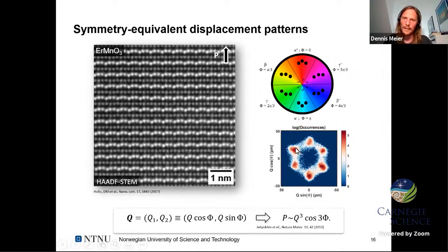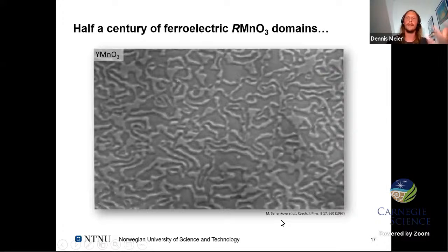When you look at order parameter space, we see these red dots here, which illustrate the 6 ferroelectric, structural domain states. And then, as I said, only as a secondary effect, due to the coupling, the polarization comes in because of these structural changes, and we also get a ferroelectric polarization. Here we no longer have 6 states, we then only have 2 states, and this is, for example, a standard ferroelectric domain pattern which you find in the manganites. The darker regions here would be one polarization direction, up, the brighter ones would be polarization direction down, for example.